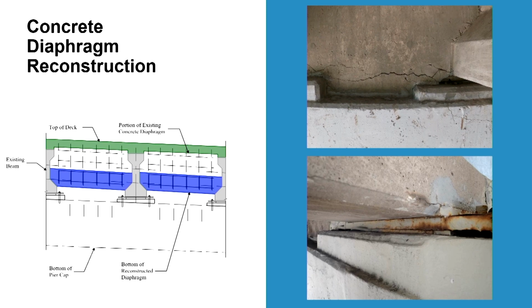And so over the 30 or so years since those have been put in place, the natural movement of the beams under live load and temperature expansion has fought against that rigidity that was built in, and so we've got these cracks that have appeared. Our approach, to hopefully put some of that flexibility back into the system while maintaining that joint closure, is that we will demolish a portion of that oversized diaphragm and build it back to just at the top of the bulb from the pre-stressed beam, so that you can get a little bit more of that natural movement and the bearings can do what they're meant to do.